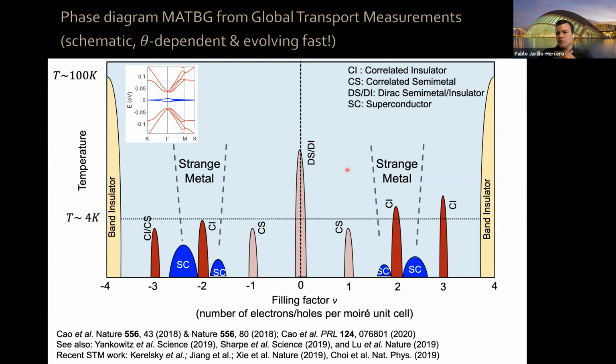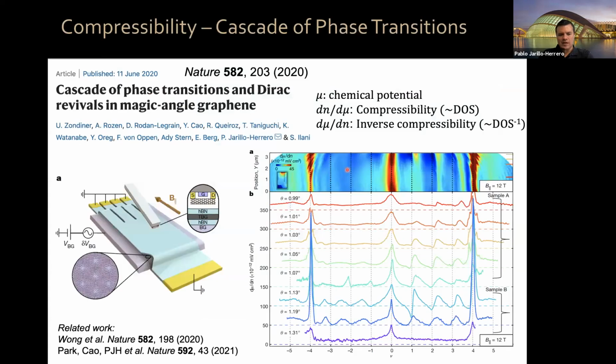Now what happens if you do thermodynamic measurements? That gives you different access to the physics of the system. So in particular, we worked together with our collaborator Shahal Ilani at the Weizmann Institute, and similar work was reported by the group of Ali Yazdani and separately later on by us. We started to do measurements of the chemical potential of the system of graphene as a function of filling factor. So mu is the chemical potential. dn/dmu, how does the charge density change in the system when you change the chemical potential? That is a quantity known as compressibility.